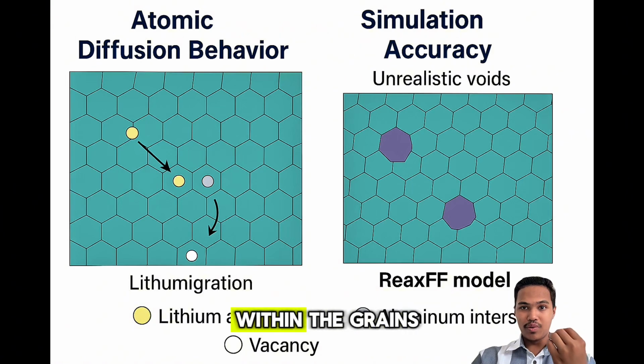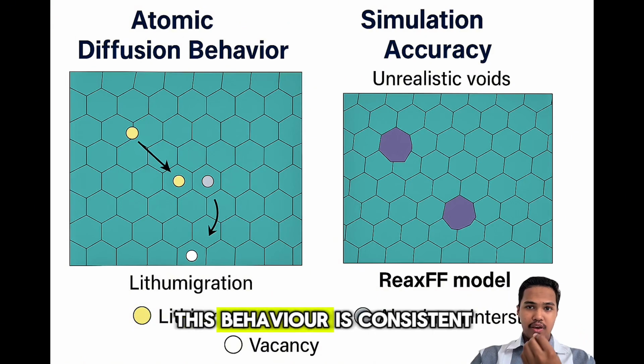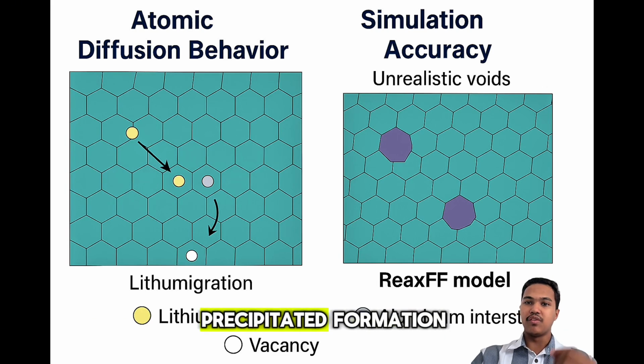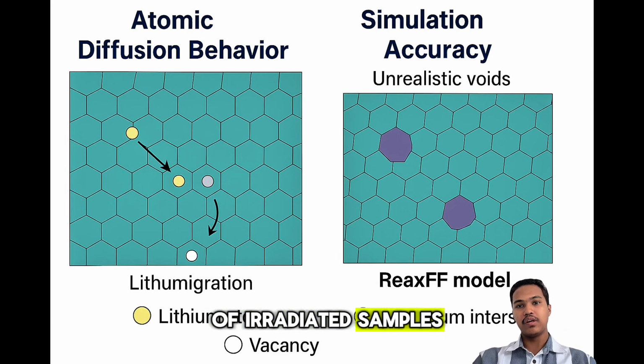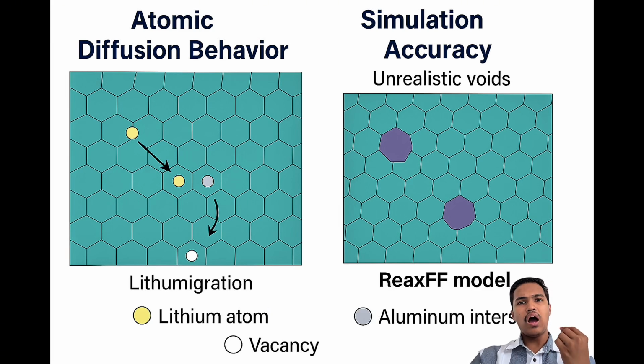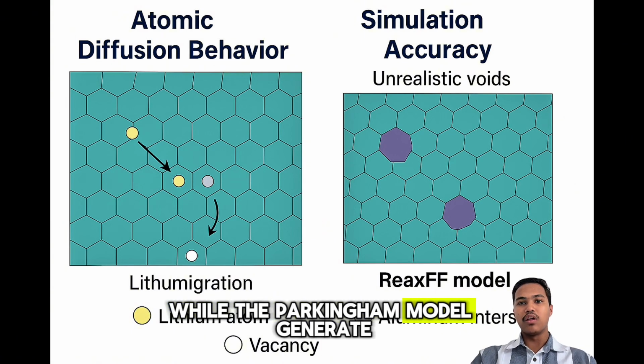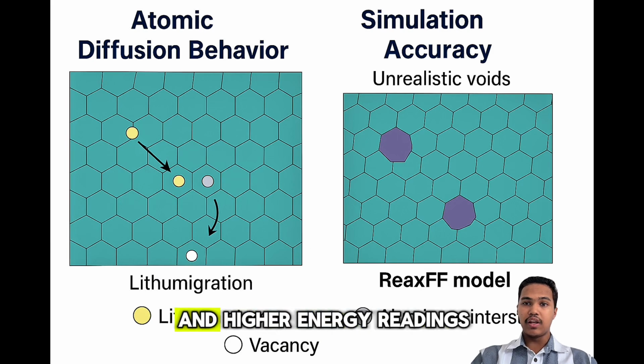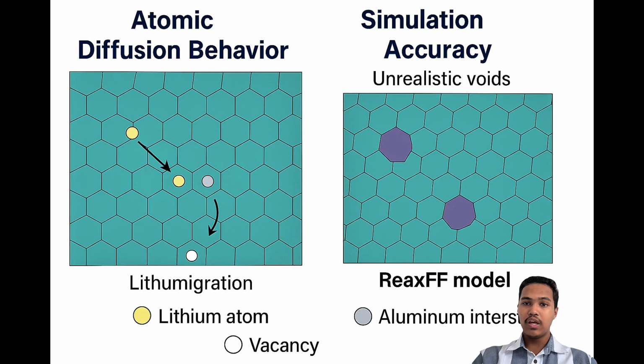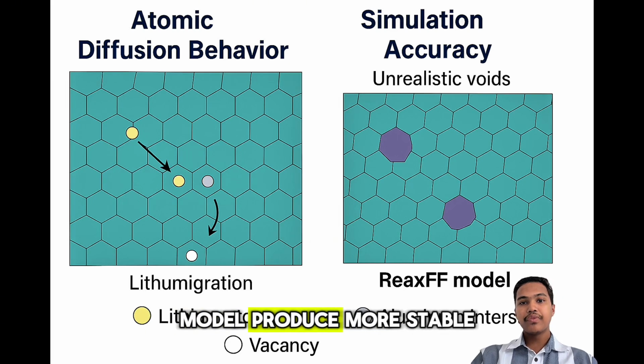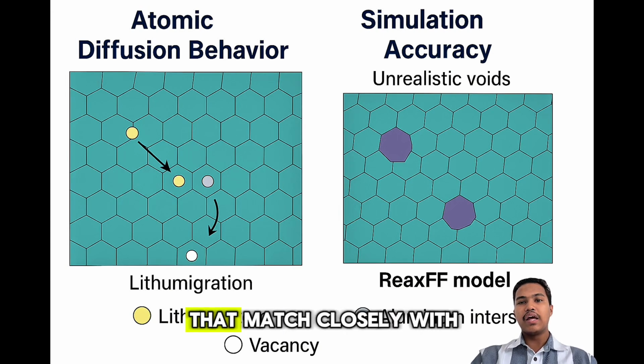Aluminum atoms, on the other hand, were less mobile and tended to remain within the grains as interstitials. This behavior is consistent with experimental observations of lithium pentaaluminum octaoxide precipitate formation in the grain centers of irradiated samples. Additionally, the researchers found that the ReaxFF potential outperformed the Buckingham potential in nearly every aspect. While the Buckingham model generates unrealistic voids and higher energy readings near grain boundaries, the ReaxFF model produced more stable, accurate simulations that match closely with the experimental data.